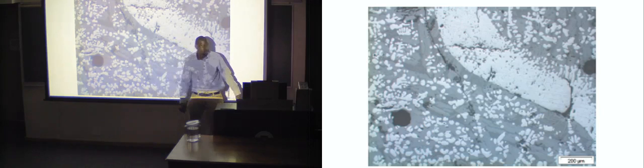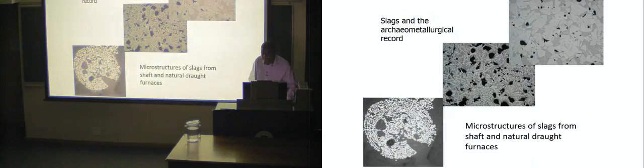So this is a photomicrograph of an iron smelting slag from Mapungubwe, and these are different phases in simplistic terms. They tell different types of information. This is magnetite. This lighter shade is more wustite, iron oxide, and these phases here are iron silicates, the olivine fayalite. So the estimates of the volume of these phases can enable us to estimate, for example, the efficiency of the reduction process and so on. So we do study these microstructures quite a lot. We also supplement them with data from X-ray fluorescence, the SEM, and other techniques.